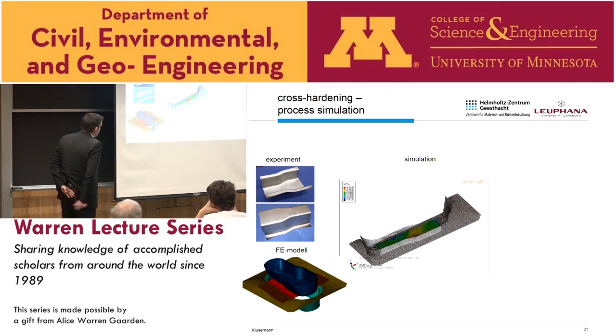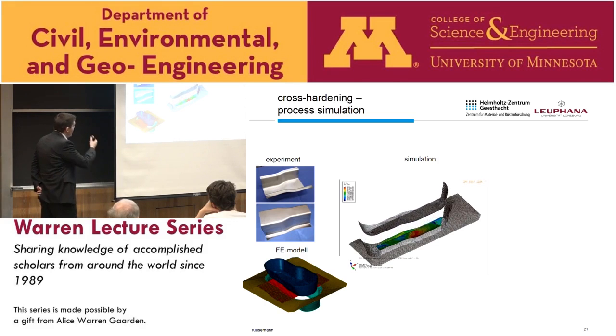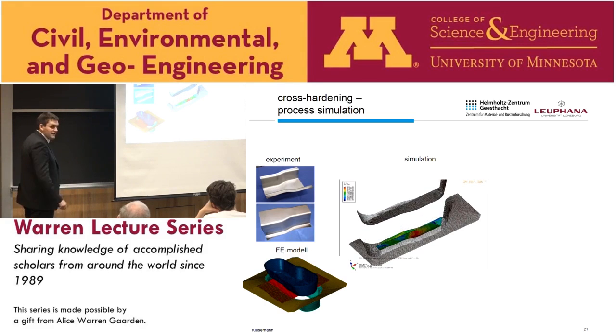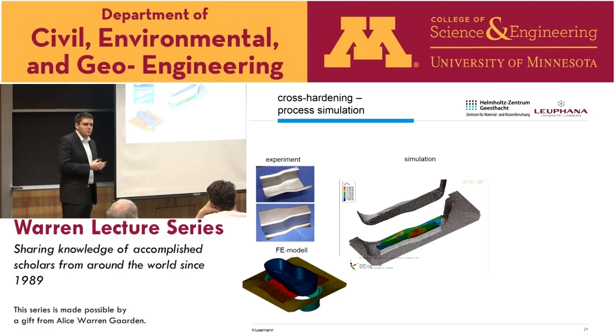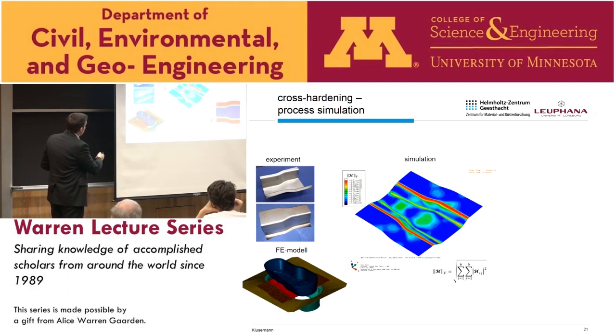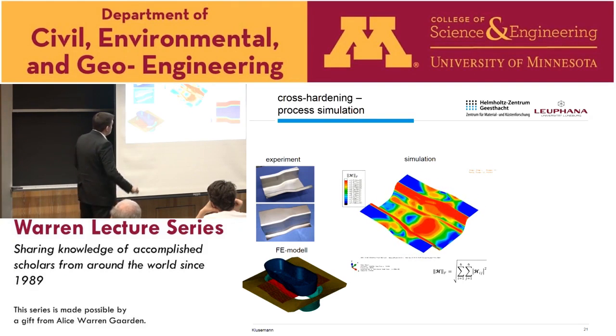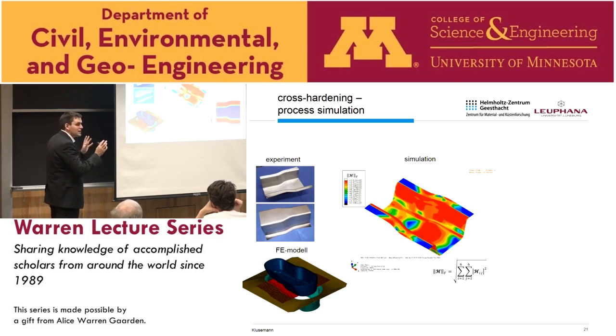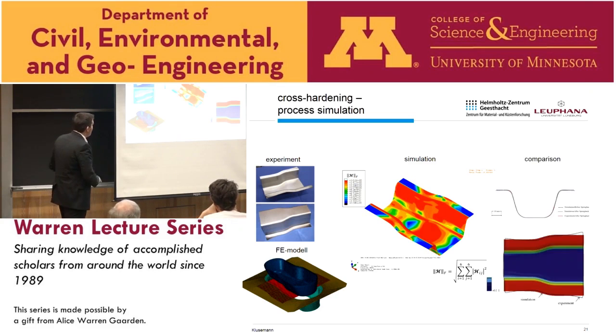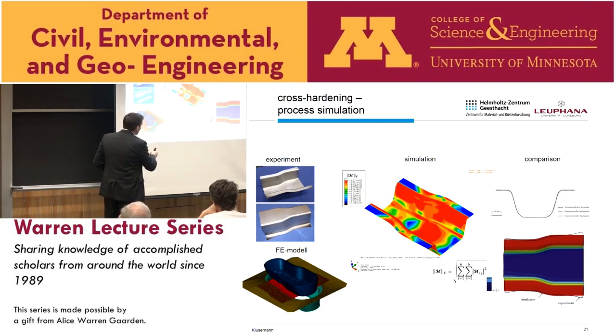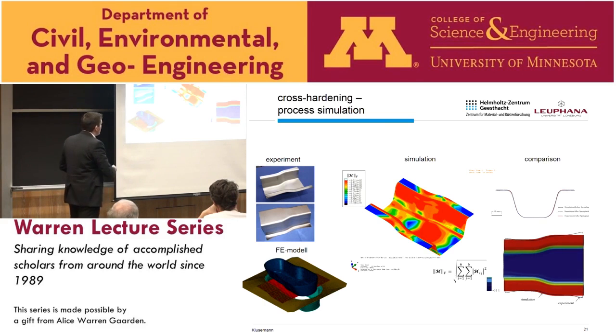So then we performed a simulation, as you can see here. We have now our complete forming process, and of course we can measure our stress level and several more features. What we were particularly interested in, because we couldn't do it experimentally, is how big the contribution from this cross-hardening actually is. This was one of the aspects we looked at. So for this, we, for example, looked simply at the norm of this cross-hardening tensor, just to have a kind of measurement of this cross-hardening.